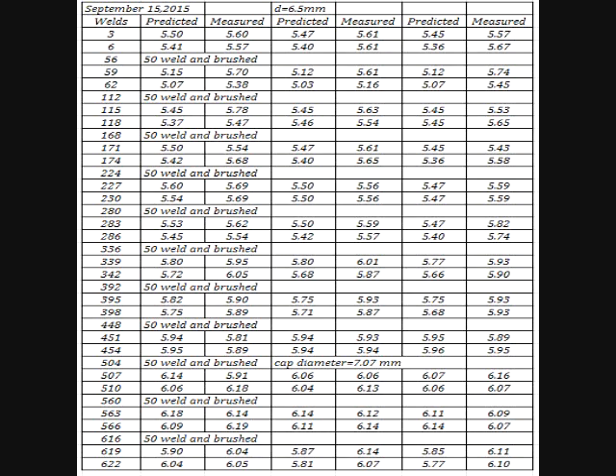We keep on doing this that day, and we started out with 6.5 millimeter with 5.5 nugget size. But after the end of 622 welds, we're getting to 6.0 millimeter nugget size, which means the weld cap has increased about half of a millimeter in 622 welds.